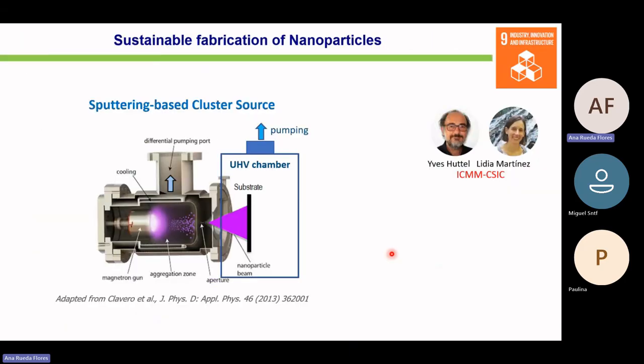So let's start with the nanoparticles. In this case, we are using a sputtering-based cluster source, which means that the substrate is not in the same chamber as the bulk. They are separated, and we can have the substrate in vacuum or in ultra-high vacuum, and in the region where the atoms are created, we can have differential pumping, so we can introduce another gas that does not participate in the plasma, but is simply increasing the pressure. If you increase the pressure, you are increasing the probability of collisions. So while the atoms are traveling, they start colliding and forming clusters. If you separate these two chambers by a pinhole, you have a beam of nanoparticles in the second chamber.